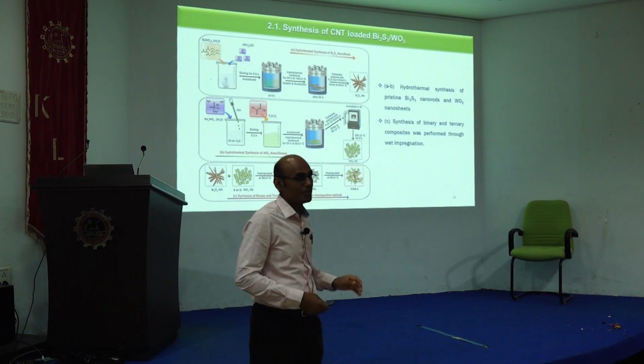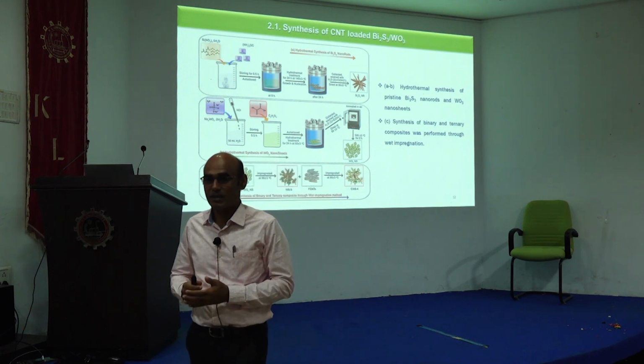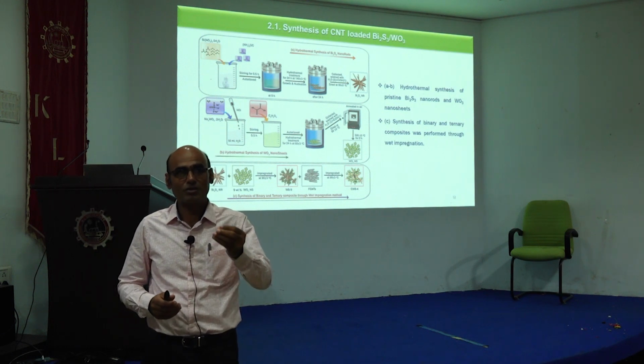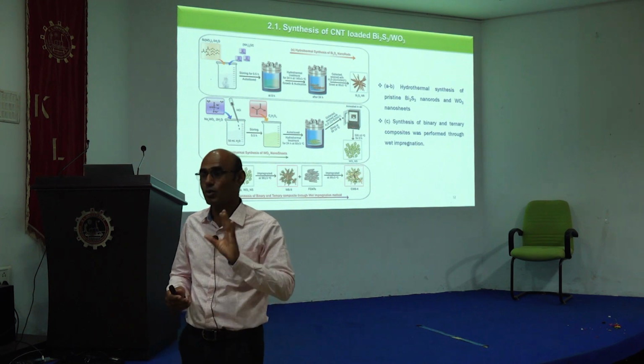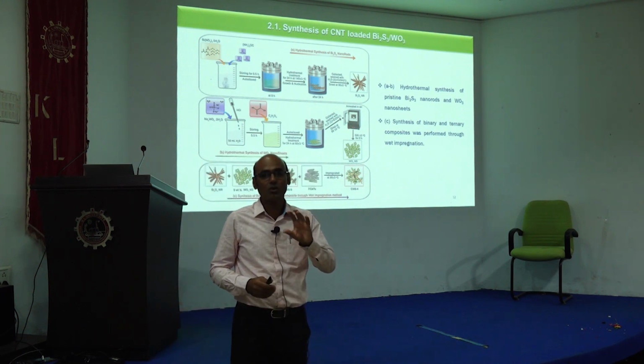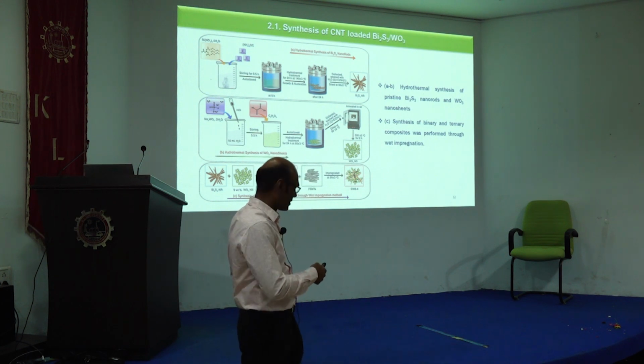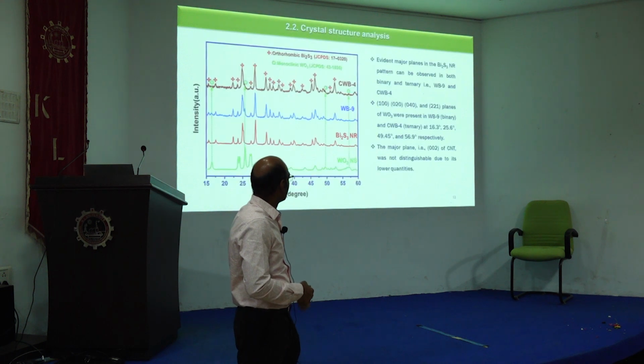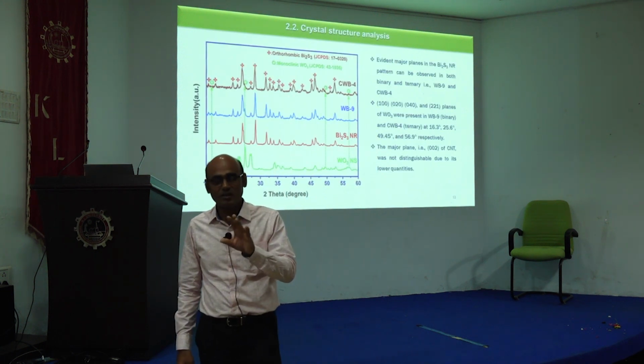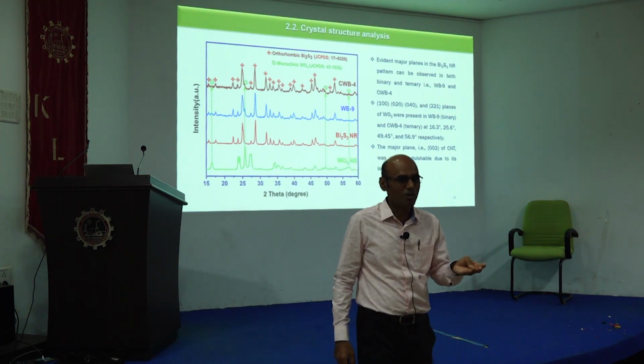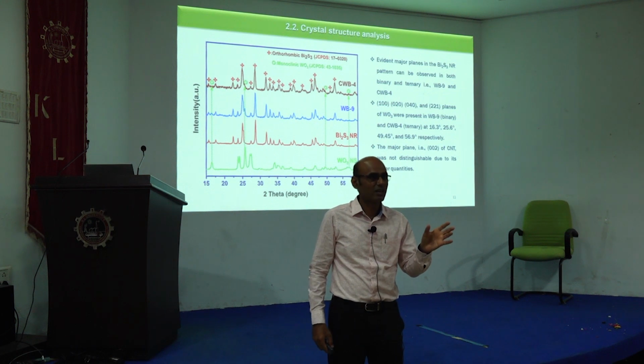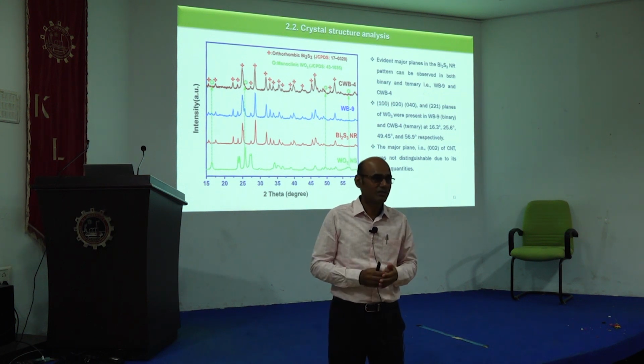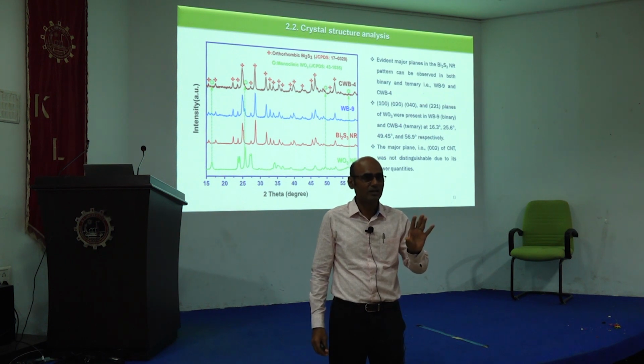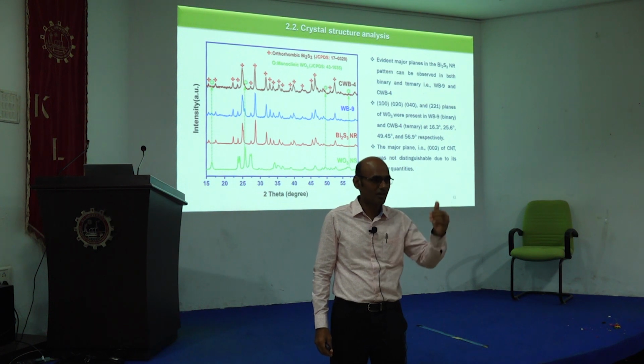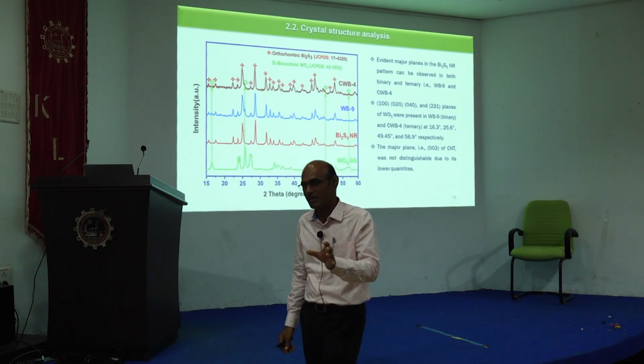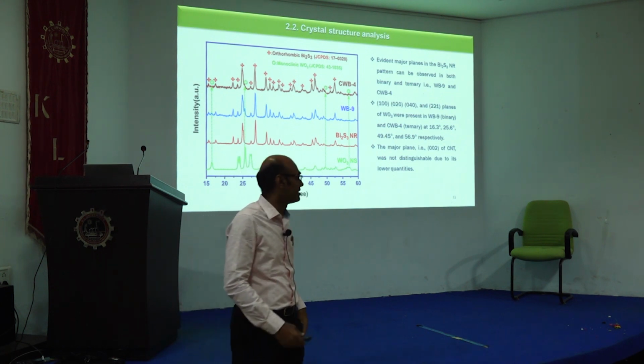So you can understand that we have prepared the material by using a very simple hydrothermal technique. A 100 ml stainless steel autoclave may cost about 20,000 rupees for a good one. You can get a lower cost one also, but a good quality one is about 20,000 rupees. To prepare this material, you need an autoclave and of course the chemicals, which you can buy easily. You need an electric oven, a stainless steel autoclave, one magnetic stirrer, and a few glasswares. That is sufficient. If you spend 70 or 80,000, including the hot air oven that can reach 200 degrees centigrade, you can synthesize this material very effectively.